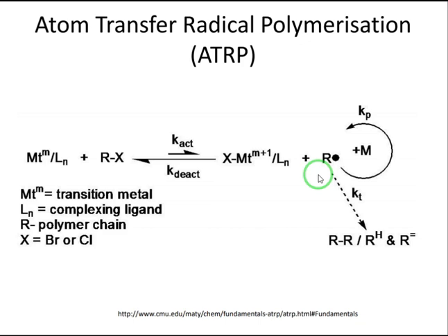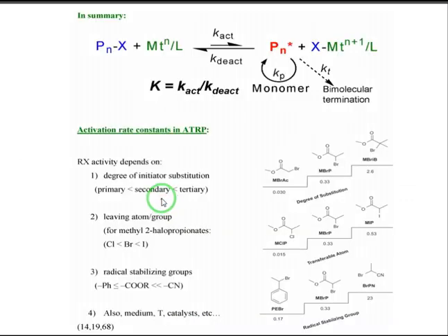So it was all about the atom transfer radical polymerization, and just remember that we are going to decrease the availability of the radicals in our system in order to decrease the termination, because the termination is going to lead to a broad molecular weight distribution.